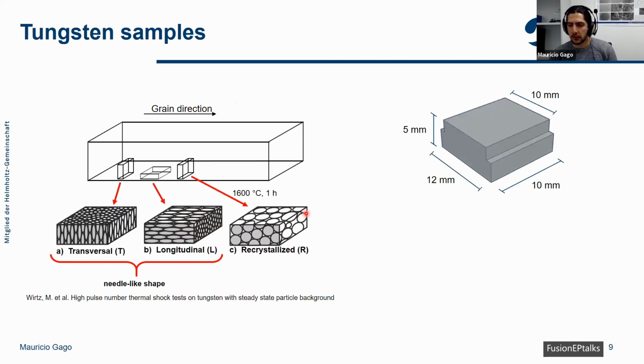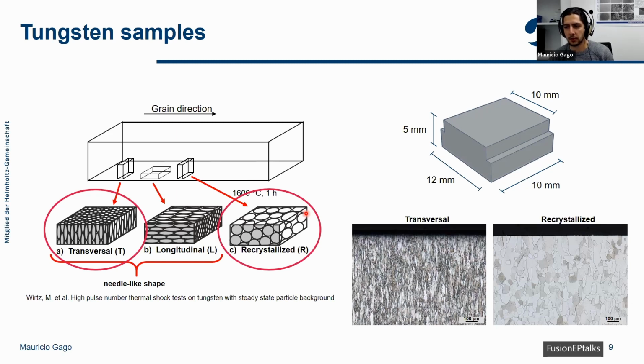So for these tests, we will use tungsten samples, which are ITER-grade. So it's basically the material that will be used, or very similar to the material that will be used for the ITER divertor. And from the original tungsten rod, depending on how the samples are cut, we can obtain a microstructure which is needle-like in two different directions, either transversal or longitudinal. For these experiments, because the transversal microstructure is preferred for ITER because of its cracking properties, this one was selected. And because under the conditions for the ITER divertor, the material might recrystallize due to being at very high temperatures for certain amounts of time, we wanted also to test this kind of material.